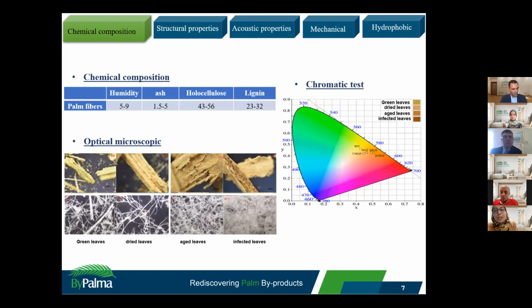However, the presence of microorganisms and the aging of the leaves during storage, as you see in the figures, may negatively impact the length of fibers. Also, for green fibers, the presence of a high amount of water may also impact negatively the bleaching process. So, based on these results, our dried palm leaves have been used in this work to produce palm fiber felts.